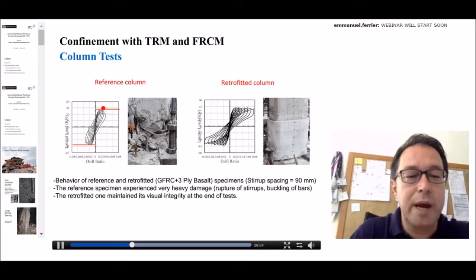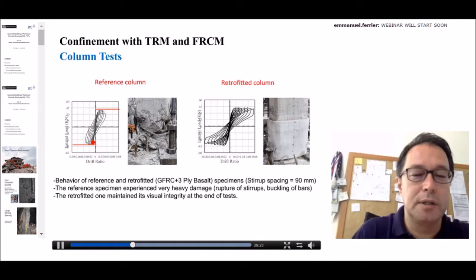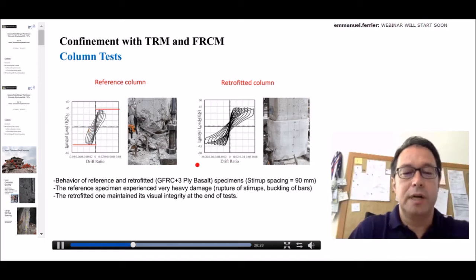Nevertheless, you see the degradation in strength at about 2% drift, significant losses in strength, and finally, for going further drifts, for the lateral displacements, you see the substantial loss in axial load capacity as well. So all lateral load capacity was lost. Also, the specimen was kind of out of control while making this kind of loading.